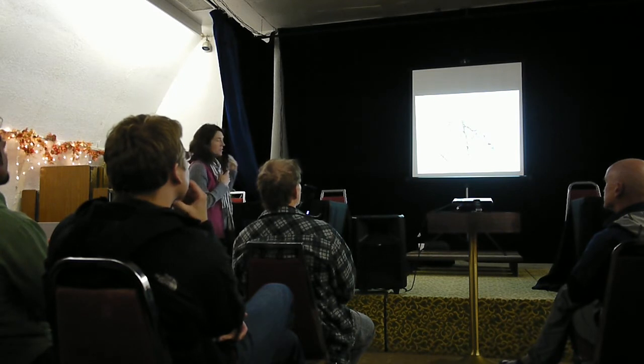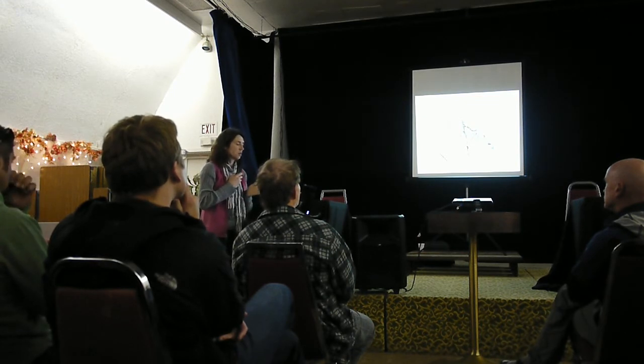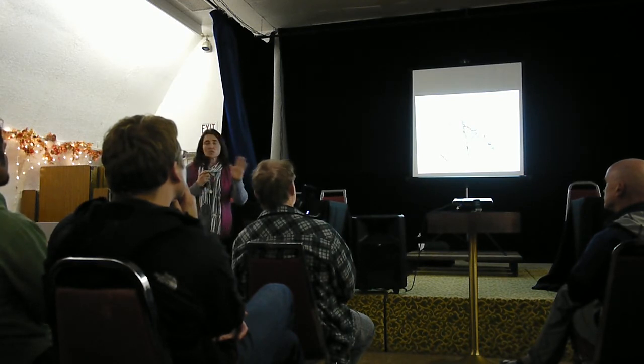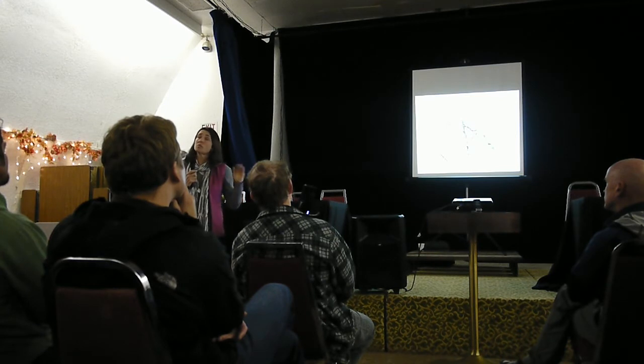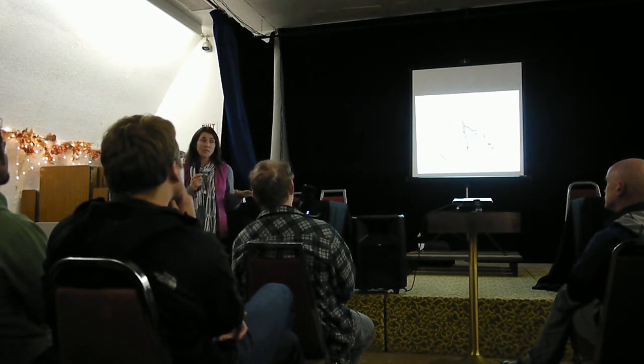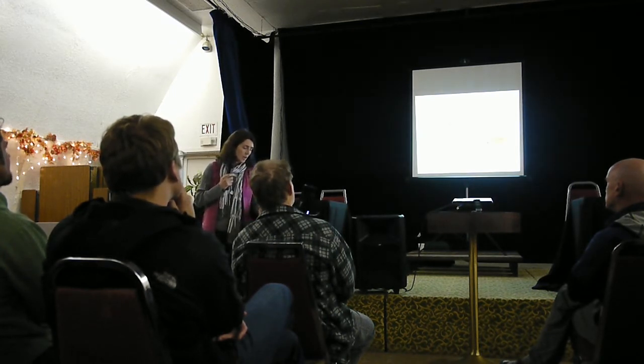And here is basically what they do. You call it etching the microstructure. So now you can see the grains, your austenite grains in this steel. And basically what you're seeing is a crack going right through those grains. So there are probably a couple of metallurgist geeks in the audience. If this was a huge litigation product failure company, I would go on and on about this because it means that the crack went through the grains instead of around them. And if the crack had gone around them, it would have said there was something wrong with the Petzl hanger. Basically, it sensitized that material, and it wasn't processed correctly. That's not the case. So there's nothing wrong with this material, and yet it was still SCC. So that was kind of a big deal, because at this point, I don't know why it's occurring in Thailand. It really shouldn't be happening.